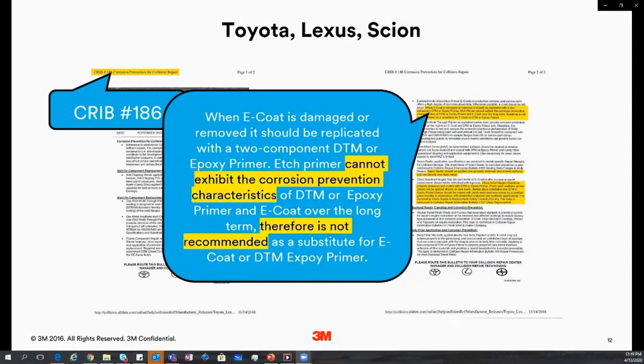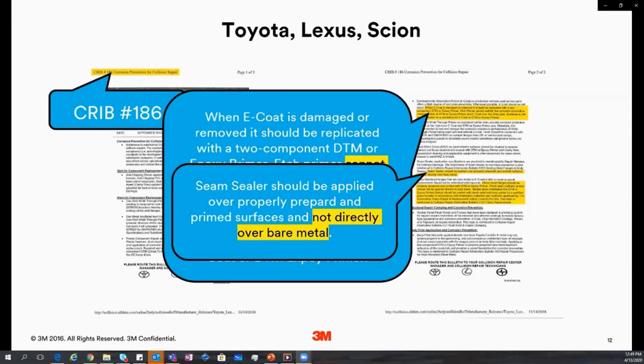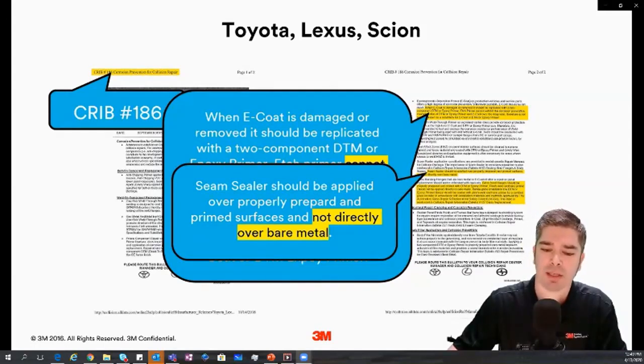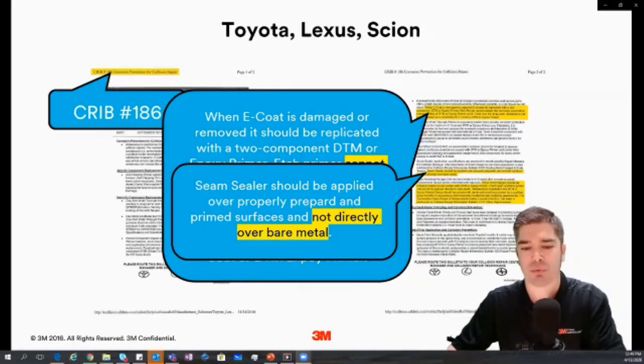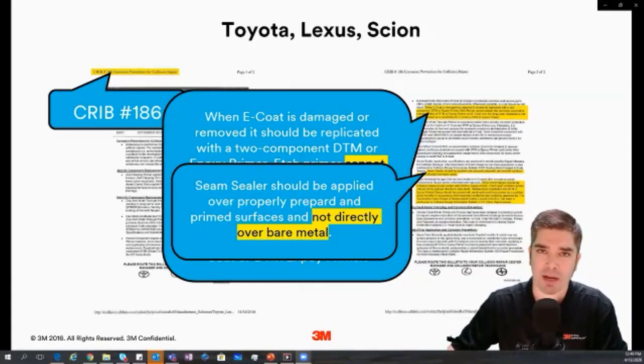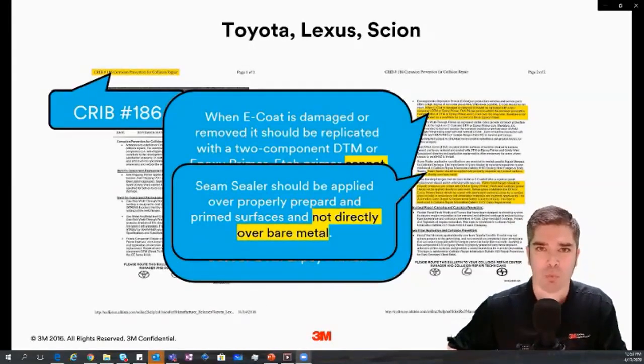And so that's very important because they also go on to say seam sealer should be applied to properly prepared and primed surfaces, not directly over bare metal. And this is a very key one to point out here because, again, if you're using a 1K primer, because you've read this statement where it needs to be put over a properly prepared and primed surface, then we really need to go back one step because right before that, they told us what kind of primer to be used, right? They didn't state a 1K primer. They specifically stated an epoxy or direct-to-metal primer. So we really got to make sure that in all aspects of the repair, we're following the OEM procedures.